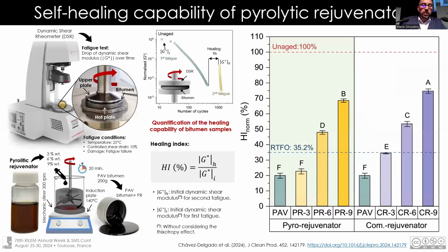The rheology of these materials, the combination with the pyrolytic oils or capsule incorporated pyrolytic oil inside, to the capability of the pyrolytic rejuvenator using a healing index. You can use the DSR test in order to stimulate the sample. You can produce micro cracks, and you heal the cracks autonomously using this material. You can design different healing index, similar to the mechanical test, in order to quantify the properties. Basically, we can increase, that's possible, by using this specific rejuvenator based on waste, a problematic industry waste.